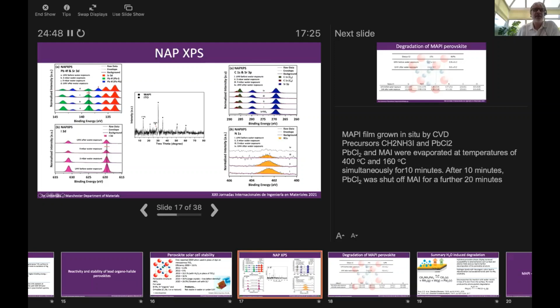The red here is the strontium from the strontium titanate substrate, which was quite useful because it allowed us to calibrate the binding energies on these samples. This is the pristine material, so measured in the ultra-high vacuum environment. We see this green peak here is the lead 4f. This is its spin orbit split doublet pair, so this is the 7/2, this is the 5/2. And this is some metallic lead, which we always find.